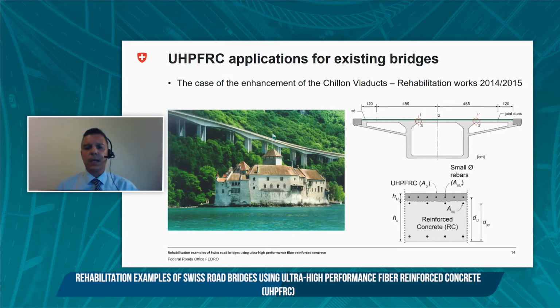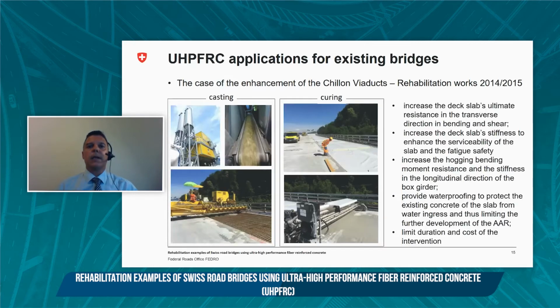The chosen strengthening concept was adding a layer of ultra-high performance fiber reinforced concrete, additionally reinforced with steel rebars in the two directions, longitudinal and transversal, also serving as a waterproofing layer. The new 45 millimeter thick layer on the bridge deck provides an effective and significant improvement of the structural performance of these viaducts. By casting one layer of ultra-high performance fiber reinforced concrete on the deck slab with rebars in the transverse direction and in the longitudinal direction, the following beneficial effects were achieved.